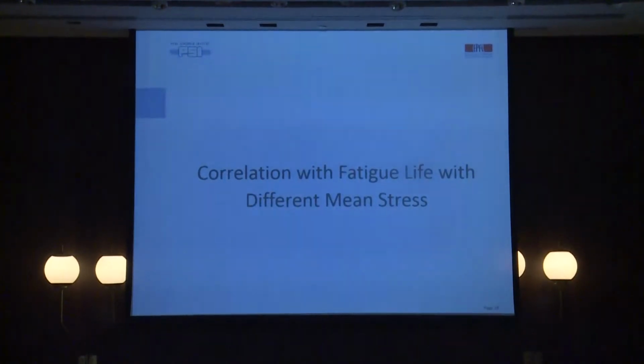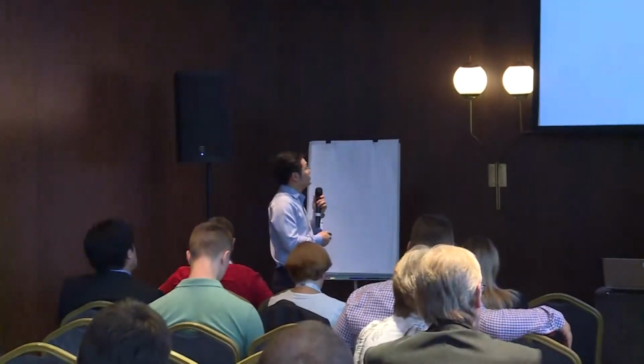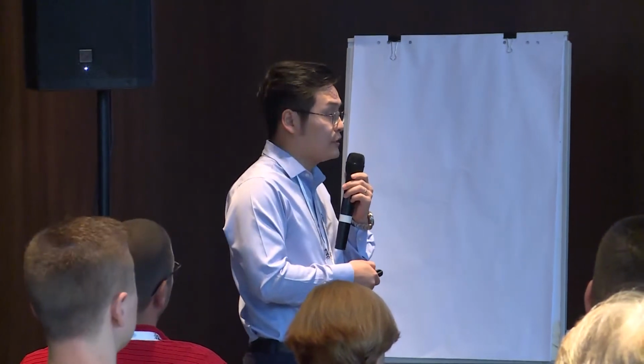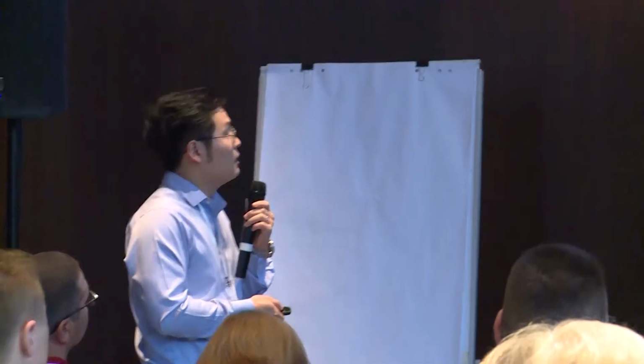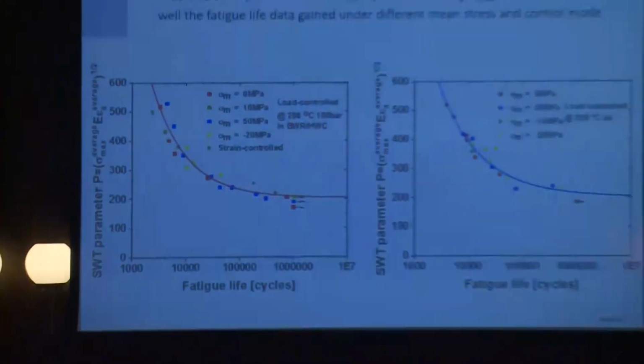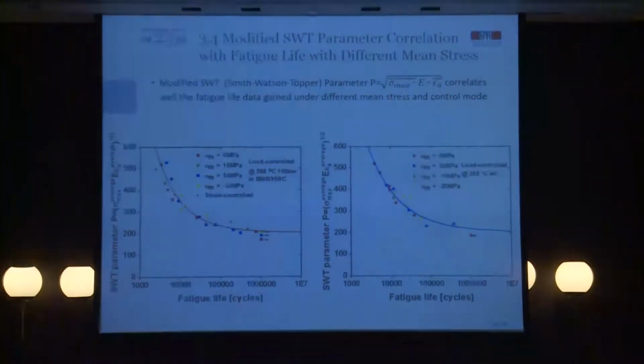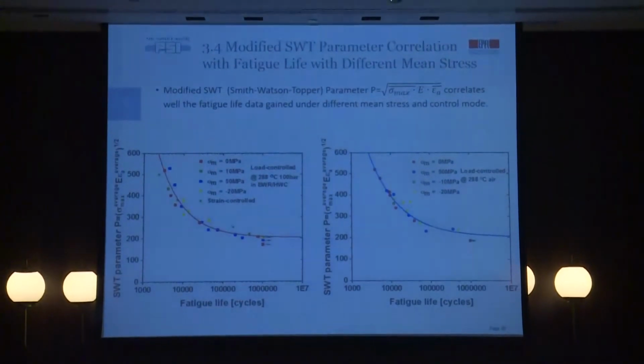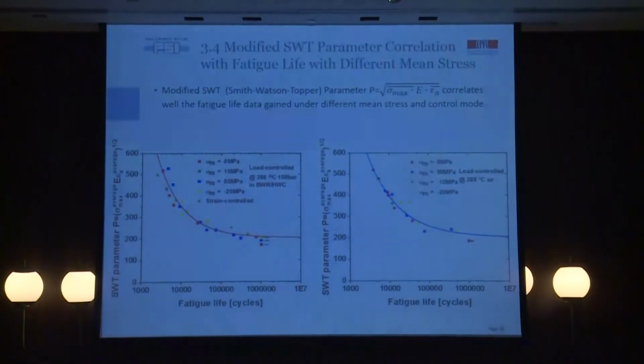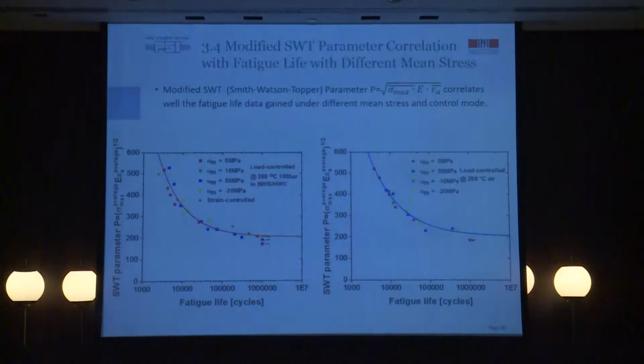After we have a phenomenal understanding about the mean stress effect on the fatigue life, on the cyclic hardening, and on the crack initiation and crack growth, we want to correlate the mean stress and try to predict the fatigue life. We applied the conventional mean stress correction models, like the Goodman model and the Gerber model, and we found they fail to correlate our tested fatigue life with mean stress.